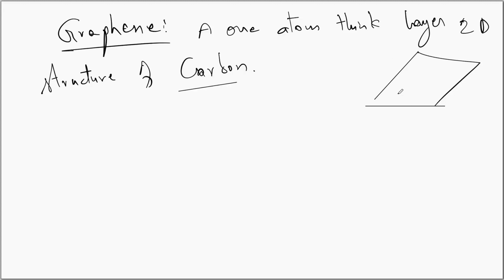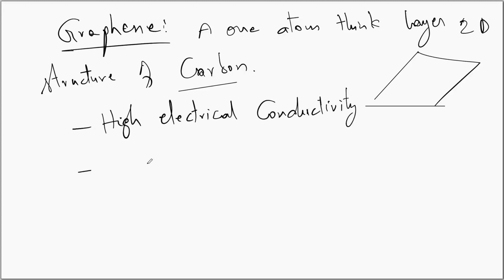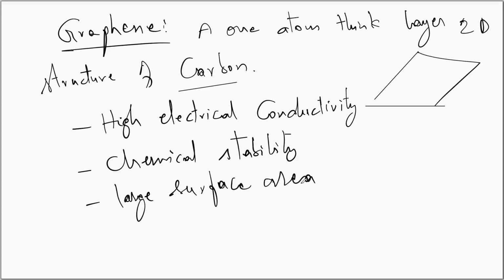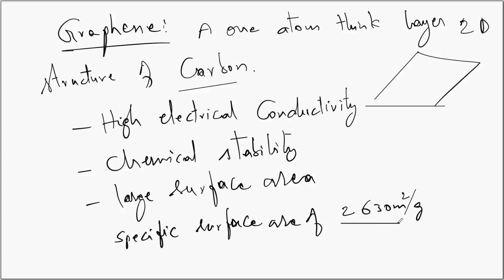Graphene has superb characteristics of high electrical conductivity, chemical stability, and large surface area. But the production cost of graphene is slightly higher. Among all the carbon materials that are used as electrode materials in electrochemical double layer capacitors, graphene is the best candidate with its specific surface area of 2630 meter square per gram. There's a huge surface area per unit mass of the graphene. So this large surface area increases the capacitance of a supercapacitor up to 550 farads per gram.